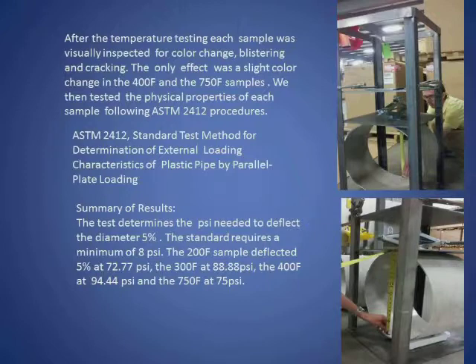Standard requires a minimum of 8 PSI. When we tested the 200 degree F sample, it deflected 5% at 72.77 psi. The 300 went to 88.88. The 400 to 94.44. And then 750 went back to 75 psi. Now, one of the things that we kind of discovered here is that essentially what we were doing was heat curing the resin and making it even stronger. That is a common practice with some resins, to heat them up to make them even stronger, give them stronger properties. But what we really wanted to find out was whether or not we were well within the range of typical vehicle exhaust applications, and we are.